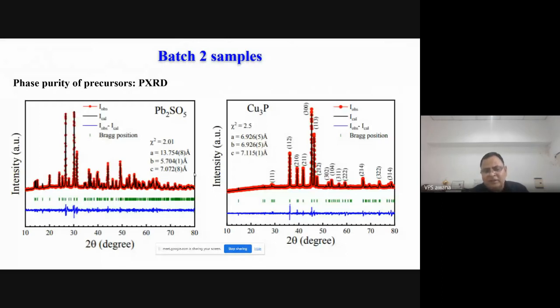This time we took the phosphorus immediately purchased, and we did not allow anything to be exposed to air. Everything was of course done in a glove box and all that. And this time our Cu3P was in fact perfect. As you can see in the Rietveld at the side, there is no unreacted copper line in the spectrum, and it was as good as, in fact better than what was shown by the Korean group.